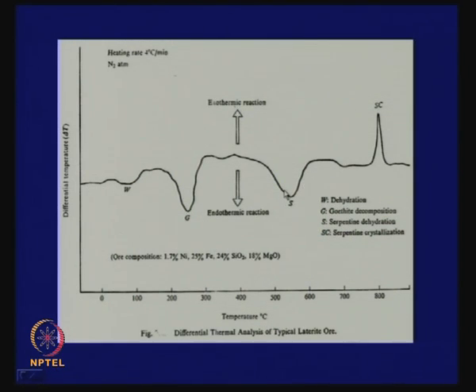This third endothermic peak, which is at about 530 degrees, refers to dehydration of serpentine. Now, serpentine is a mineral which is there in the ore. Its composition is Mg6Si4O10(OH)8. It is a very complicated mineral. This oxide in the serpentine becomes active above 600 degrees. The next exothermic peak, this is very critical. The serpentine phase crystallizes, that Sc at about here shows crystallization of serpentine.